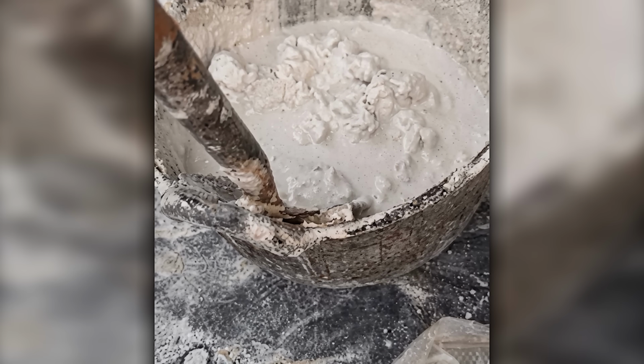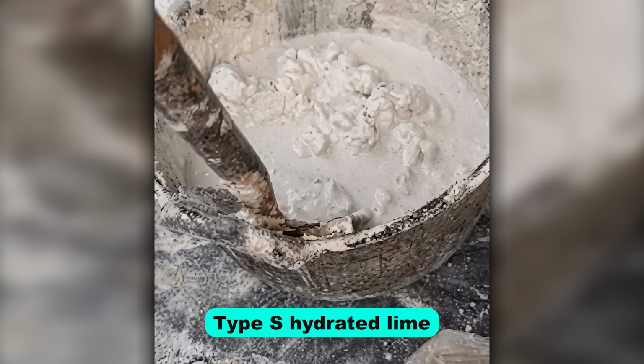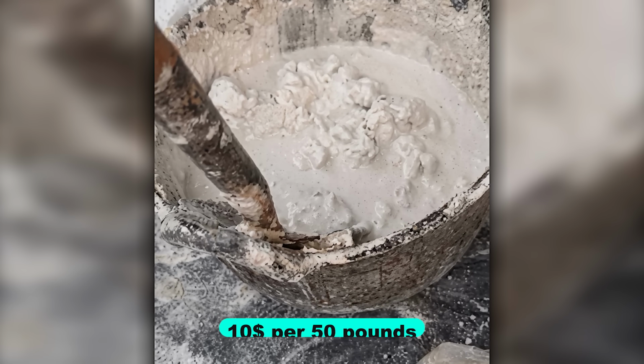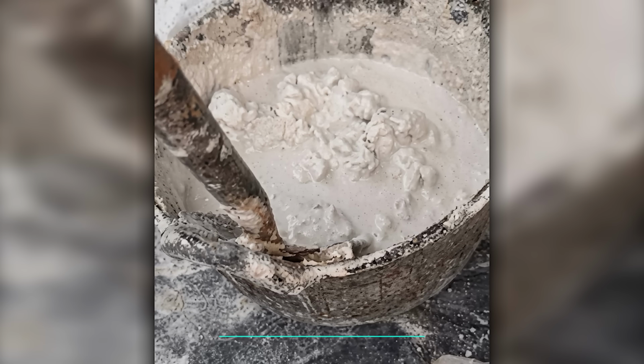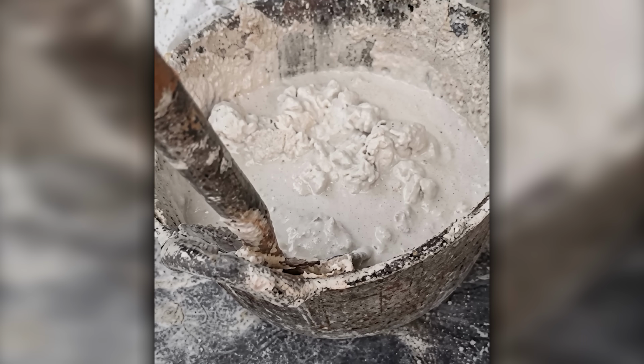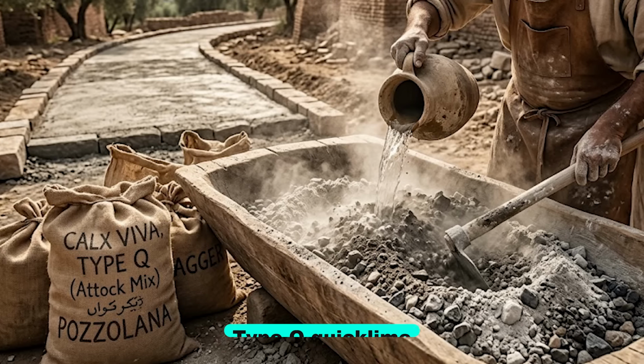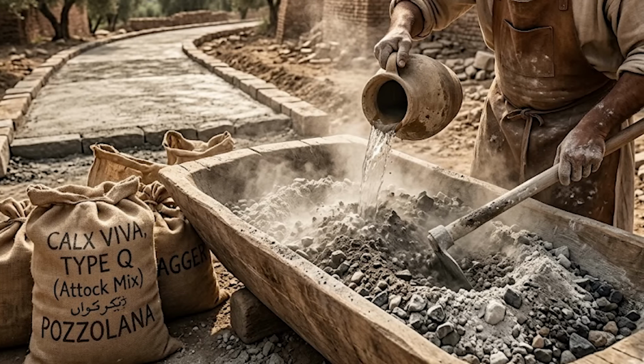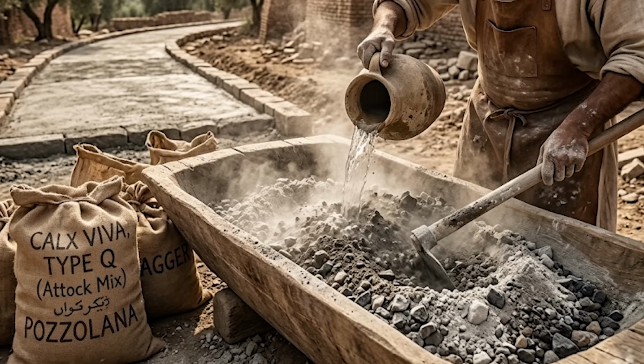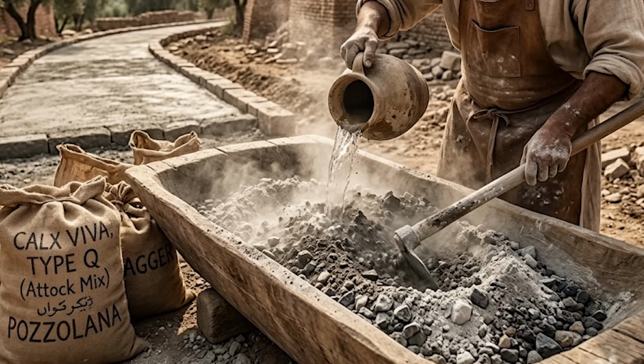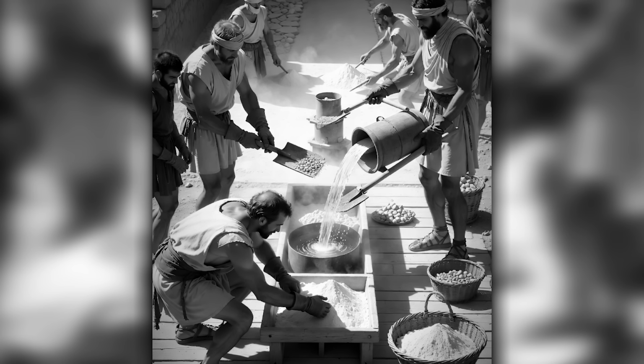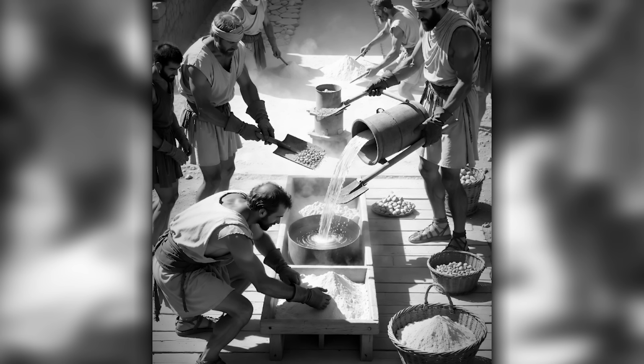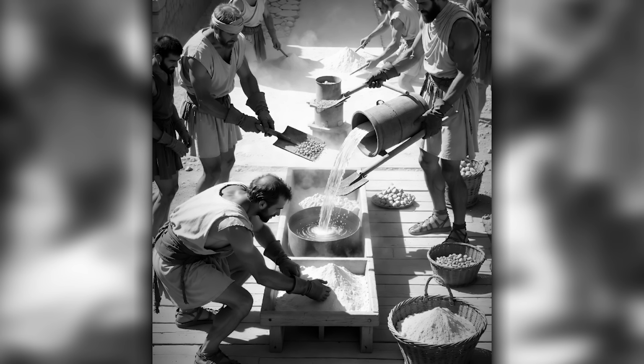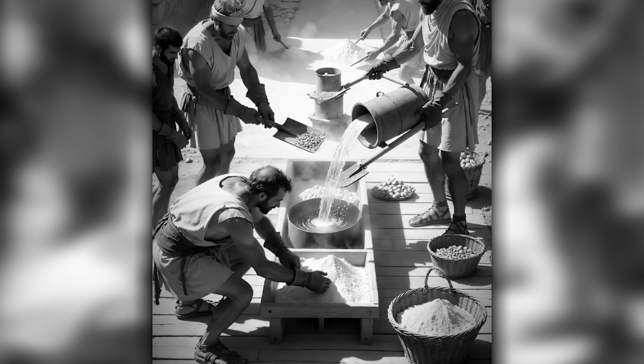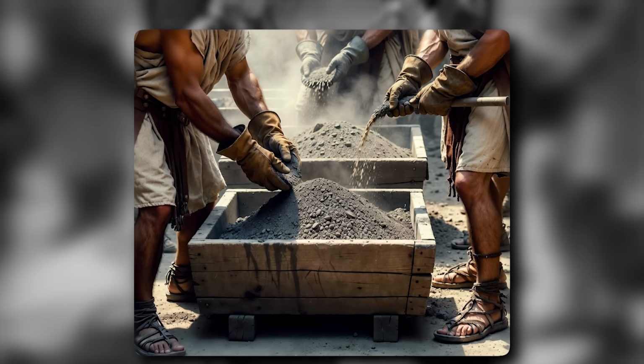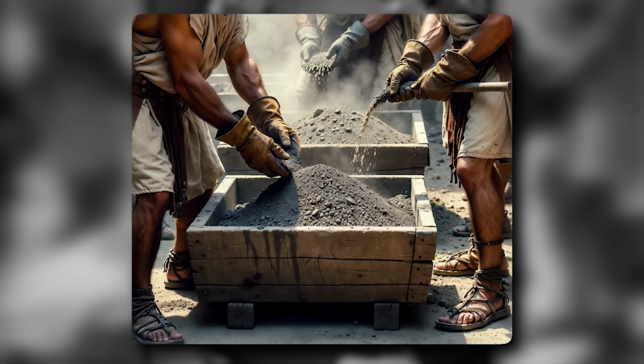If you want to try this yourself, the safe path is Type S hydrated lime, $10 per 50 pounds, mixed with water before the other ingredients. The Roman path is Type Q quicklime, dry mixed with your pozzolan and aggregate, water added last and fast. The Roman path bakes the self-healing clasts into the wall. It is also caustic enough to burn skin on contact. Leather gloves, safety glasses, and a respirator are non-negotiable.